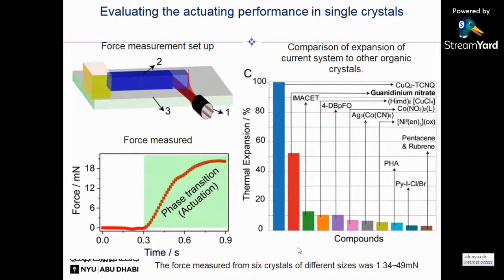Apart from this behavior, we have also quantified the force generated by these crystals during the phase transition by using a force sensor. We place a sensor on the crystal during the phase transition. We can quantify how much force has been generated by these molecules. We have tried 6 different sizes of crystals. We have observed from 1.34 to 49 millinewtons of force.